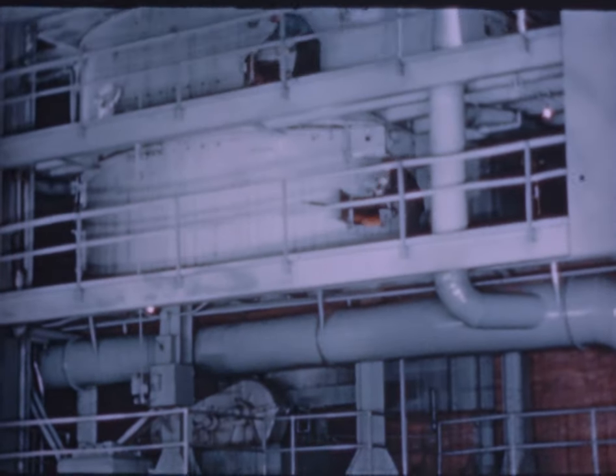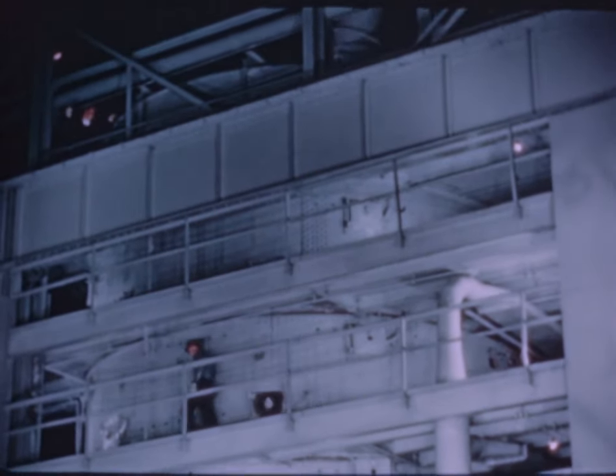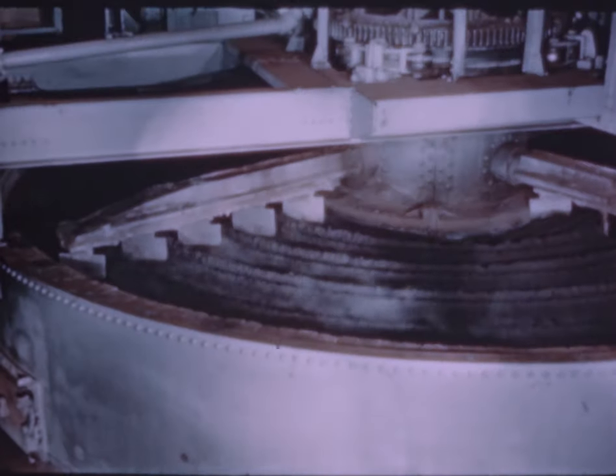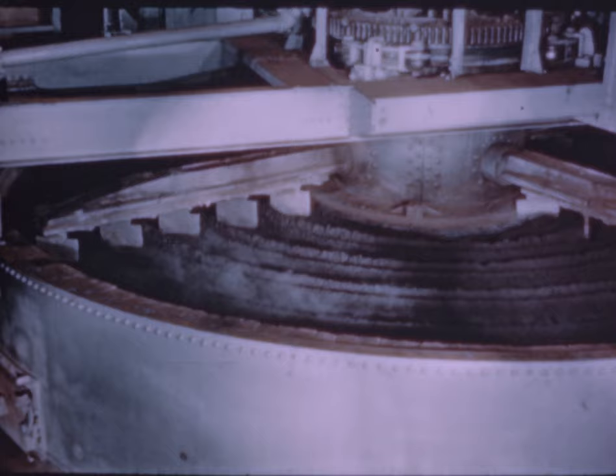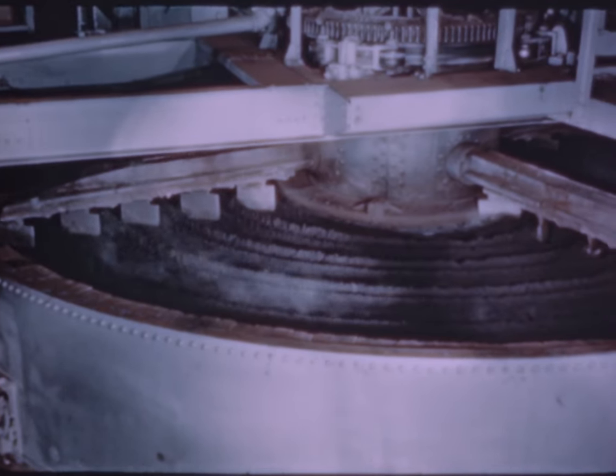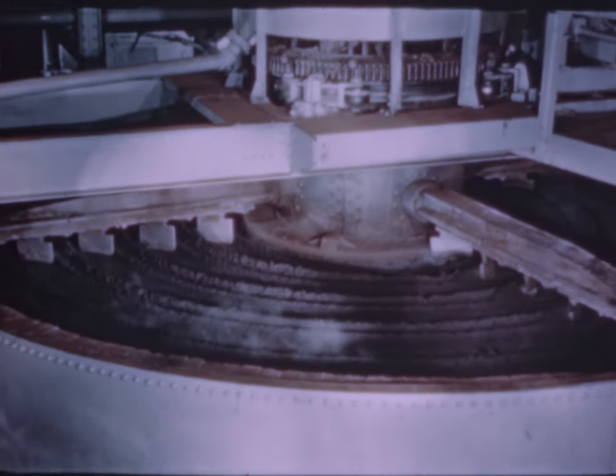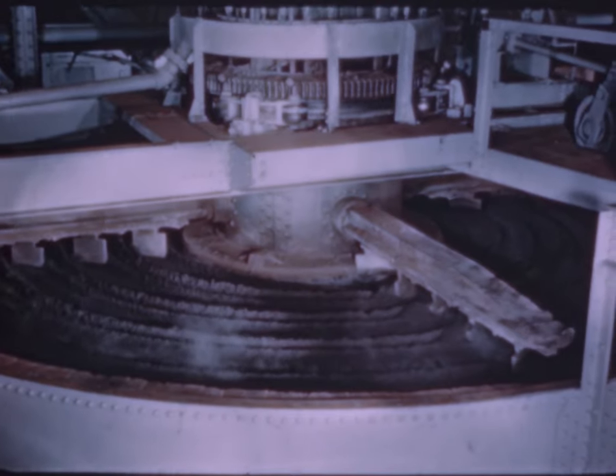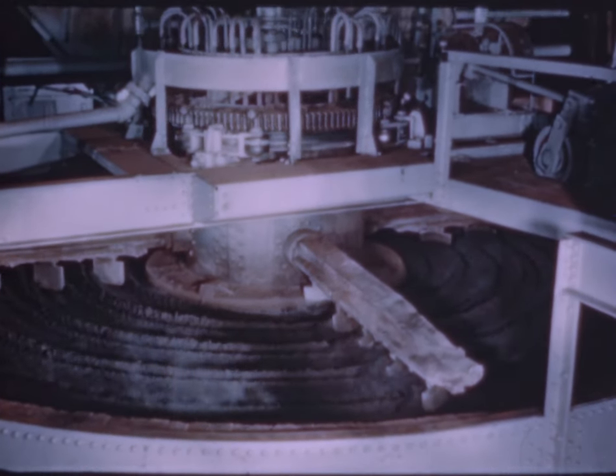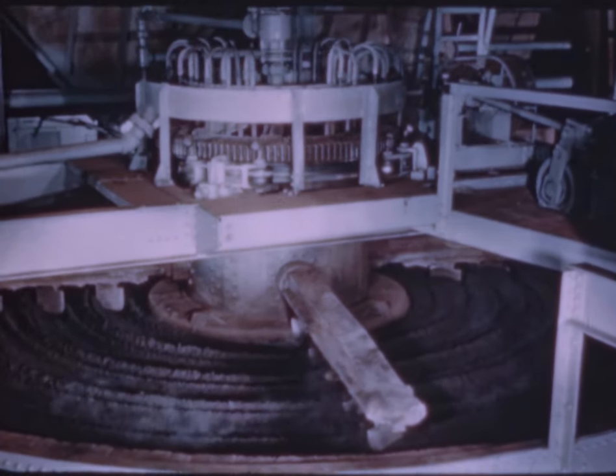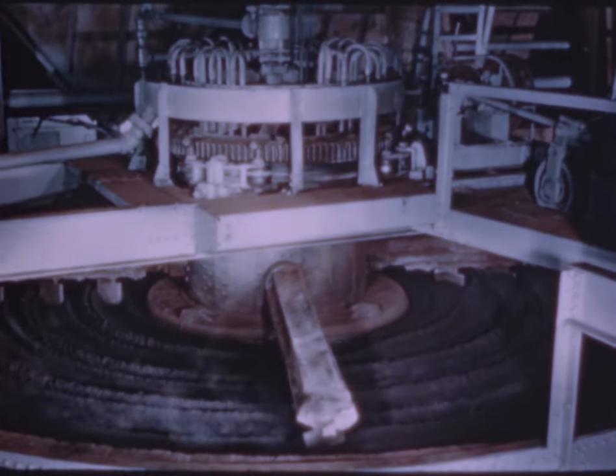Here, too, in Great Falls is one of the world's largest zinc plants, with a rated capacity of 15,000 tons of cathode zinc per month. Zinc concentrates, as received, contain many impurities, most of which must be removed before the zinc can be recovered by leaching. In these multiple hearth roasting furnaces, sulfur is burned out of the zinc concentrates, and certain other elements are oxidized.